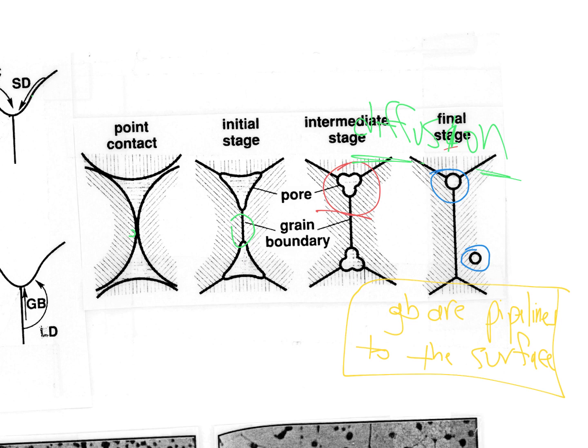All right, but they're what we're stuck with when the sponge stops. We lose that connectivity of the porosity with the exterior surface. We're stuck with diffusion. And of the two choices we have grain boundary-based diffusion, where these things just move along the grain boundaries and eventually find their way. And when I say things, of course I mean air, if we've done it in air. So we have oxygen, diatomic oxygen, diatomic nitrogen, and what happens is those guys go from being diatomic molecules to being ions, and they migrate out as ions, which is one of the reasons why it's so slow. All right, and so they diffuse along those grain boundaries, and obviously that's not as good as the sponge, but what's even worse is when this guy is not on the grain boundary.